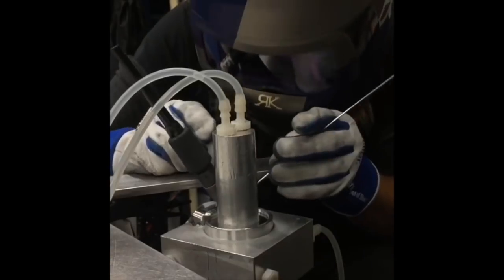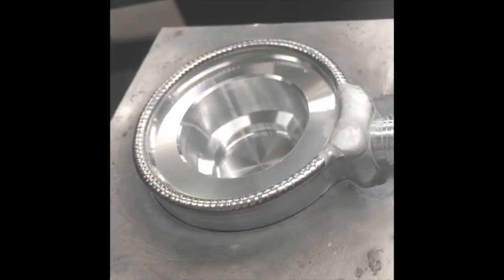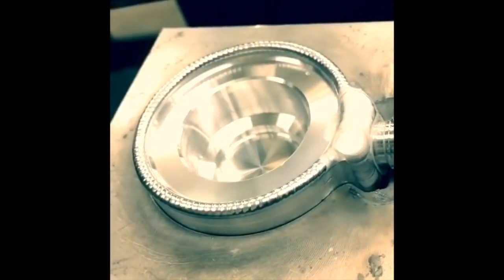Yeah, so I run a lot of outside aluminum corners on 063 aluminum, and I have this jig. It's a clamp, and so it has aluminum on the backside for a heat sink to keep that thin gauge aluminum from warping, and then it has a stainless clamp that sits on top of it to hold it down and hold it together, so I can set my edges exactly how I want them to be set up for the weld.